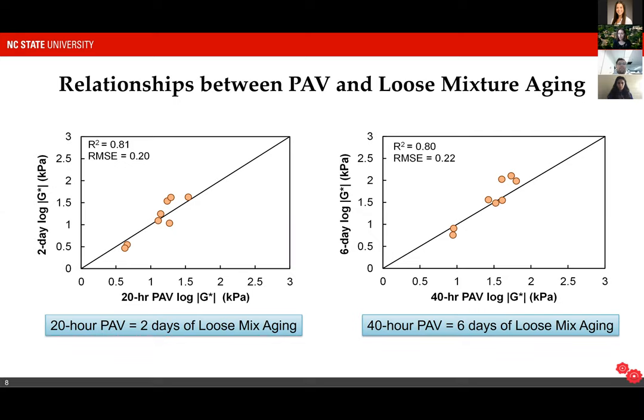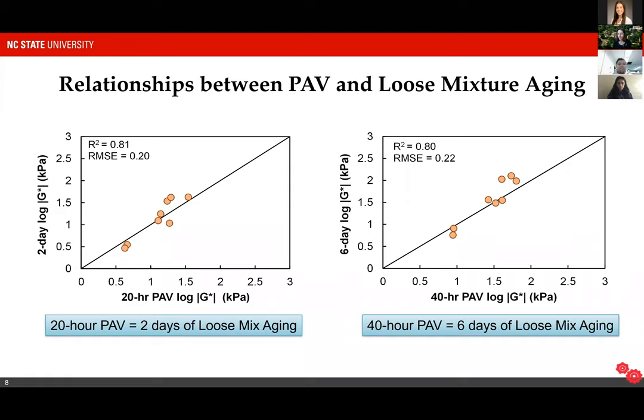We used this in combination with our link between the PAV aging procedure and corresponding duration of loose mix conditioning to achieve the same rheology. I'm showing those relationships for two PAV age levels: the standard PAV procedure of 20 hours of conditioning, and the 40-hour PAV procedure — included because it's become quite popular in recent years as many have suspected the standard procedure doesn't mimic prolonged field aging. For the 20-hour PAV aging procedure, we found it equated to approximately two days of loose mixture oven conditioning at 95 degrees Celsius. In the case of the 40-hour PAV aging procedure, it equates to roughly six days of loose mixture conditioning.